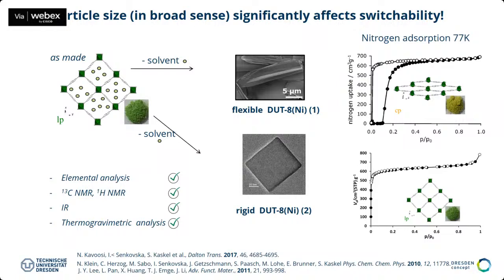So in essence, they show different desolvation behavior. This one stays in the open pore form, and this is actually also a metastable form in the end. Because from thermodynamics, it wants to contract, but because of the higher surface energy, it stays in the open pore form. Actually, when you heat these crystals to higher temperature, they also start to contract. At 200 degrees centigrade or something like this, they also start to contract. But there's also some sort of decomposition, or some rearrangement. We also find a different form. Therefore, this cannot be used to make the CP small particles.